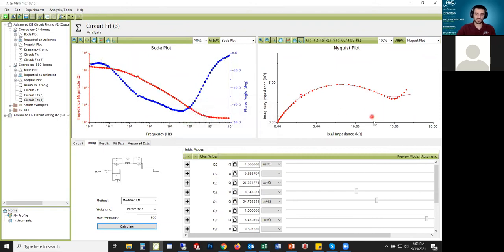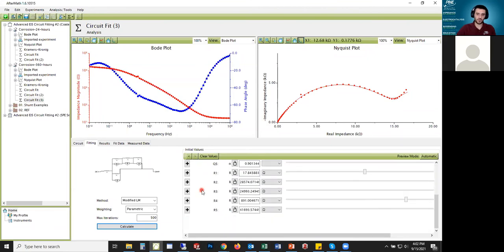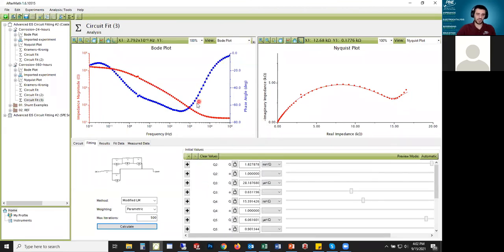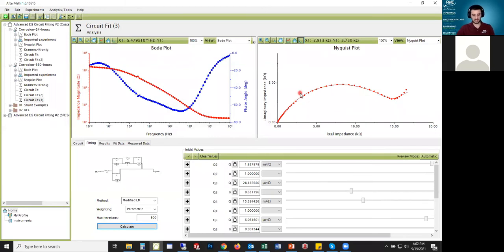Whenever you can have a real application of your circuit model, that makes the most sense because you can apply it to reality. You're not just adding, oh if I just throw another capacitor in here, I can get it to fit better. Because that doesn't always mean anything in real life. If you can get it to mean something, you're going to have a more powerful argument for why this circuit fit perhaps makes the most sense to your data. Hopefully the algorithm will find a good fit here. And actually seems to fit pretty well right away. One of these CPEs is always getting beyond the limit, so I'm going to increase that range here. This is definitely a better fit here. I've got this curvature much better and it's really capturing the Nyquist plot a lot better than the previous one.